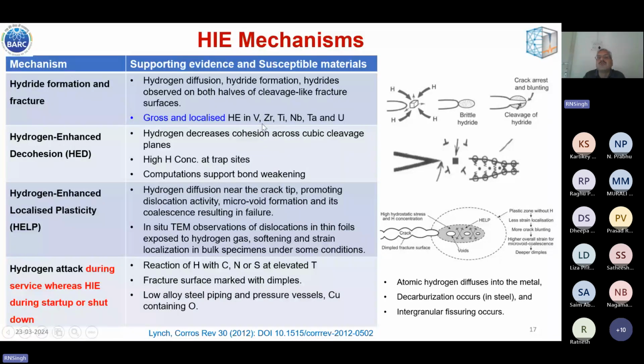So suppose you have got a notch. Because of application of load, there will be stress concentration. Because of this concentration, hydrogen first will migrate toward the crack tip, and here hydrogen concentration will increase. Once hydride precipitates, then what happens? Brittle hydride has formed near the crack tip. Hydrides are brittle, so the crack will grow through it, and then again it will wait for the hydrogen to move to the crack tip. So this is the mechanism of delayed hydride cracking.